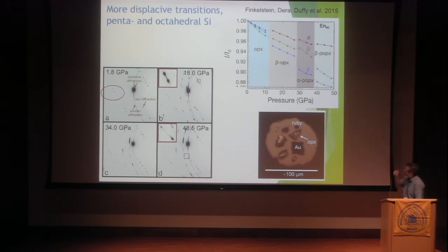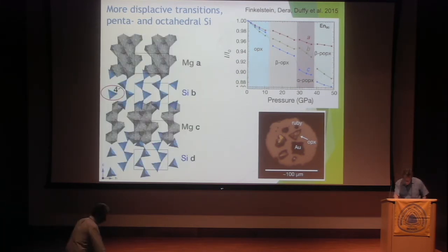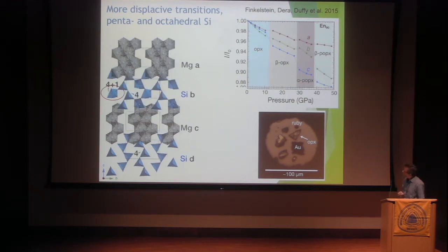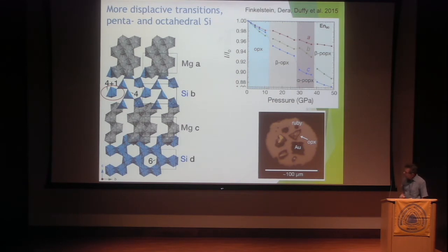We studied a variety of orthopyroxenes over a range of pressures, and we found that these samples actually undergo a whole series of similar structural phase transitions, which further change the symmetry, further affect the density. And then finally, at around 40 gigapascals, we find something interesting happening. So this is enstatite 90, a sample with 90% magnesium and 10% iron. You can see that there's a phase transformation which changes the coordination, where it's marked with a circle, from a normal 4-coordinated silicon to a 4+1. So we have an additional bond which is a little bit longer and forms this state that is known from synthetic compounds of pentacoordination. And then at higher pressure, the other symmetry-independent silicon becomes 6-coordinated, so we have a mixture of 5- and 6-coordinated silicon.